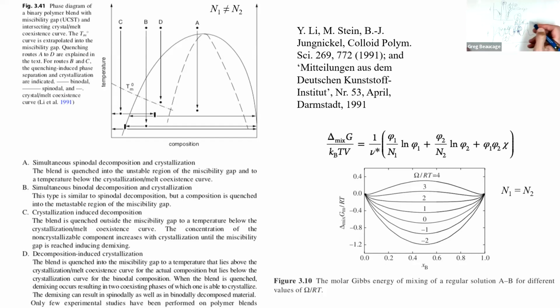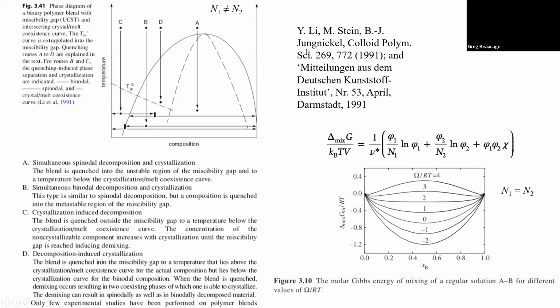So anyway, spinodal again ends up giving you this kind of web structure that has some kind of spacing to it, some characteristic spacing size. If you shoot a beam of light through it, you get a peak. You can get a spinodal peak where 2 pi over that angle gives you that spacing. And that spacing you can calculate from the diffusion coefficient and the chi parameter. Right, so anyway, that's that business. I think that's in the notes somewhere.